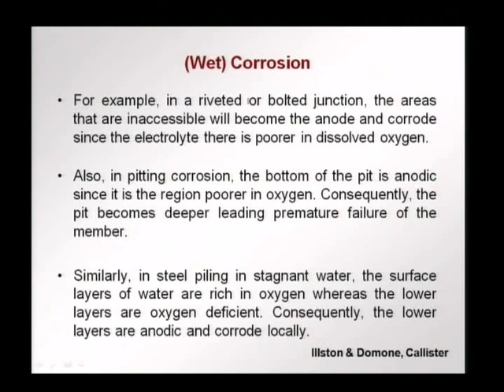This also we see in pitting corrosion. The bottom of the pit is further away from the surface and therefore, it gets less oxygen. This region is poorer in oxygen and therefore, becomes anodic. The consequence is now that the pit becomes deeper and deeper, leading to premature failure, which again happens because in an inspection we see only the top surface, we do not see the depth of the pit, and the depth of the pit could reduce the section and cause a defect to be formed, which can become a crack later.